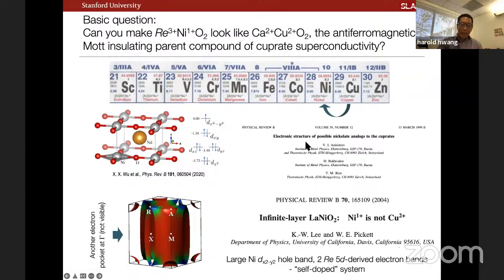So indeed, if you are able to synthesize this layered nickelate compound using a lanthanide as a spacer layer, then you do get a nominal d9 configuration. So this looks very analogous. And that was the starting point of this first paper.